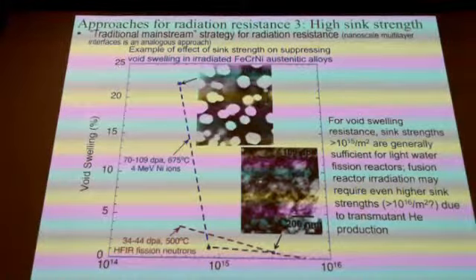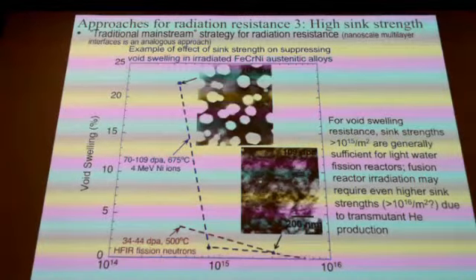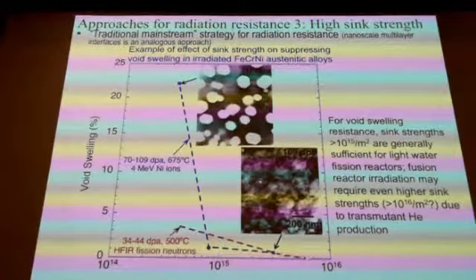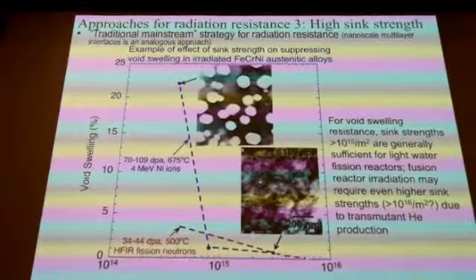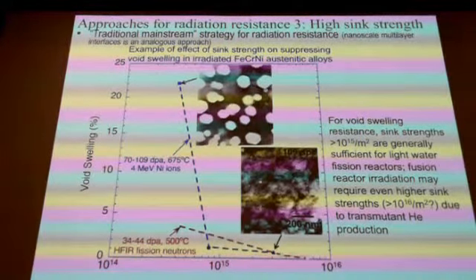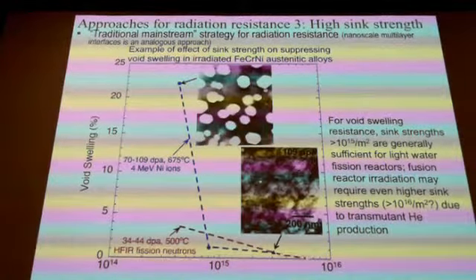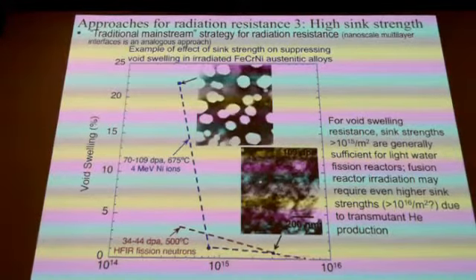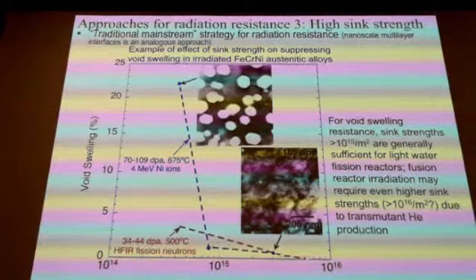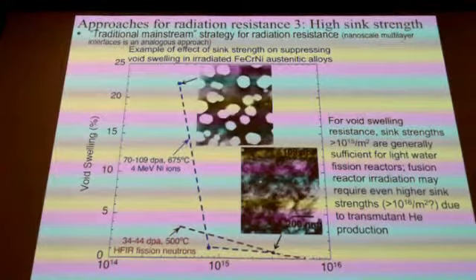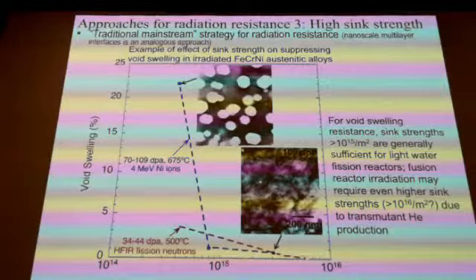Then the third category for designing in radiation resistance is utilizing what's called a high sink strength. In this technique, you can imagine, you've created mobile interstitials and vacancies in the material. If you could introduce some defect recombination centers, just think of them as like a parking lot or a skating rink, at some point a vacancy would hop into this parking lot, and it doesn't get released from that parking lot. And sometime later the interstitial comes along and it also hops into that parking lot, and then they're locally combined or confined in this region. The vacancy and interstitial will eventually recombine with one another. And that's the general concept for coming up with high sink strength materials, which has proven over the years to be a very effective way to get high radiation resistance.